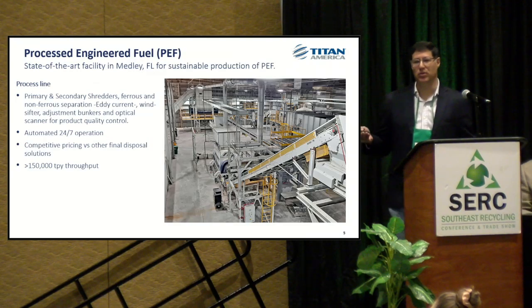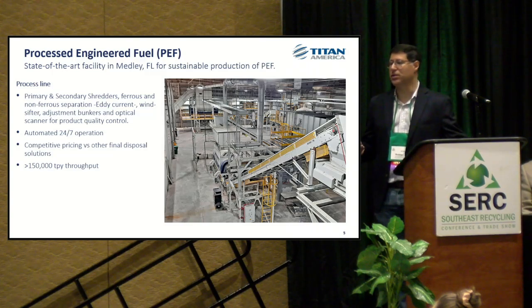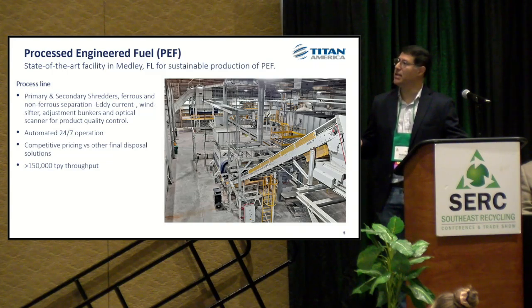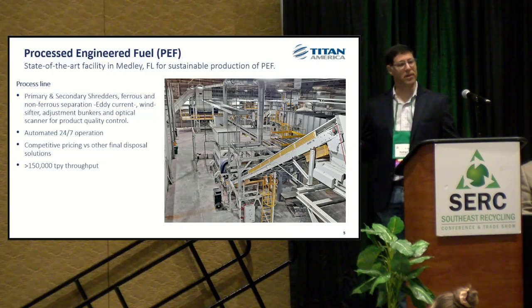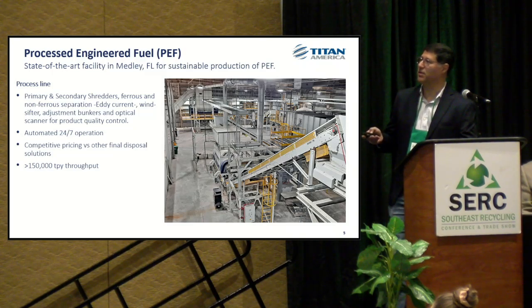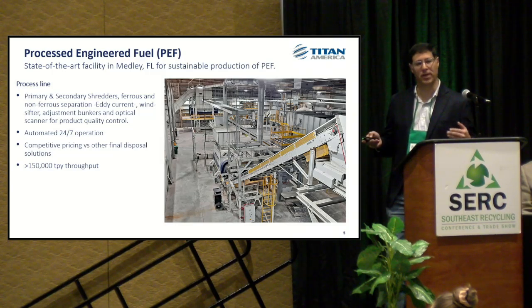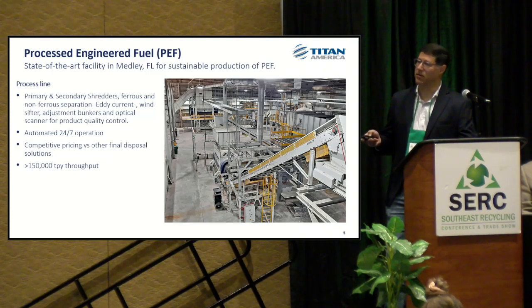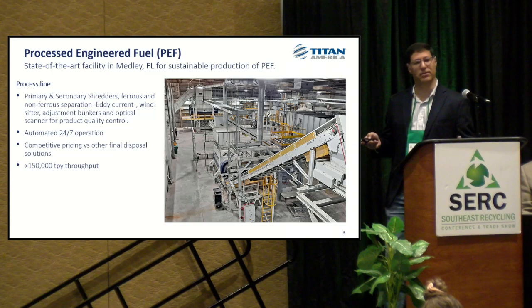And what we did, again, 5 years ago, we started this journey. We finally commissioned it 2 years ago, and we have what I would say is the state-of-the-art and most modern facility in the state. We have our primary and secondary shredders, all the bells and whistles, eddy current, wind shifter, adjustment bunkers for moisture, and we have an optical scanner for quality control. We monitor the chlorine level and the moisture level all the time, with automated operation 24/7, and basically a very competitive price versus other landfills or other disposal solutions. We have a capacity of around 150,000 tons per year processing here. Right now we are around 60, 65, so we have a lot of room to grow.